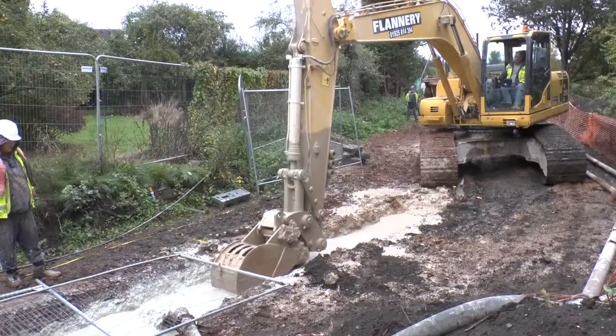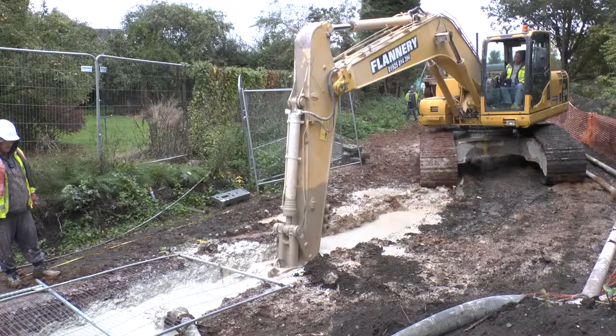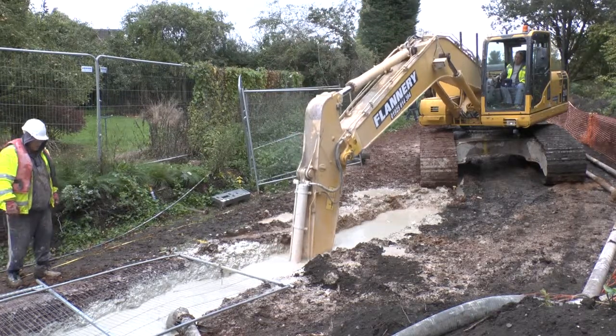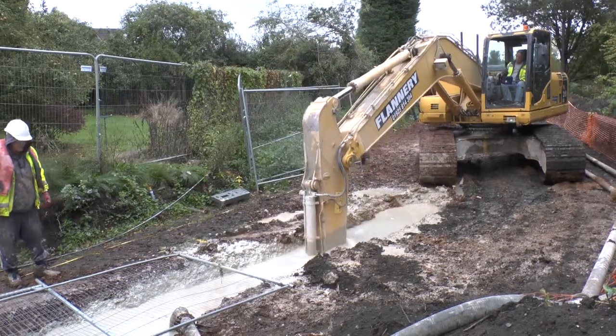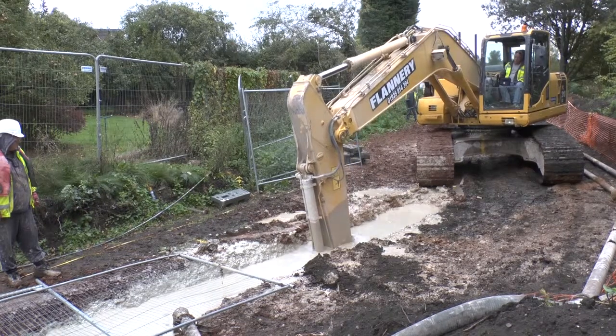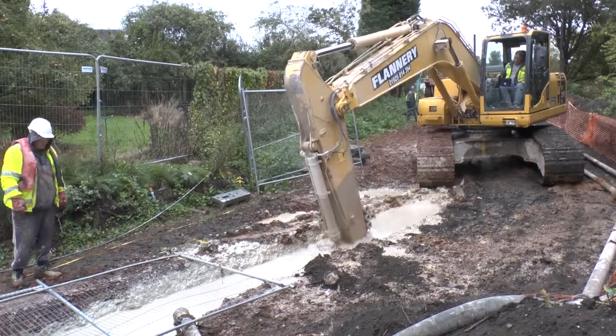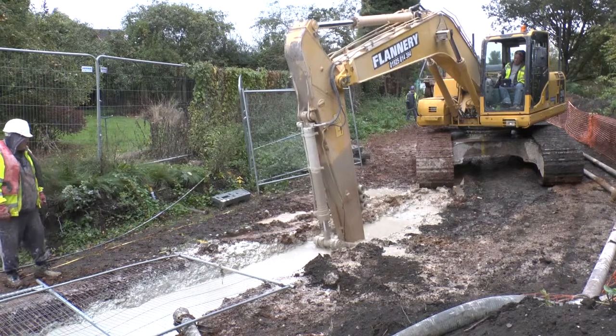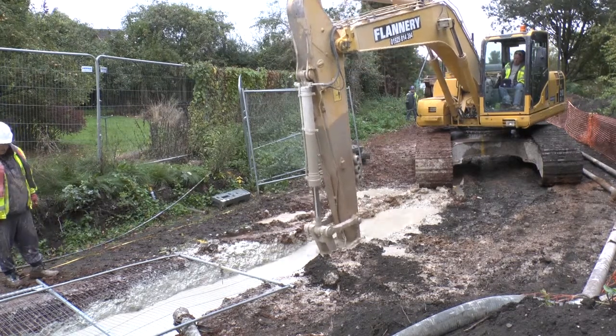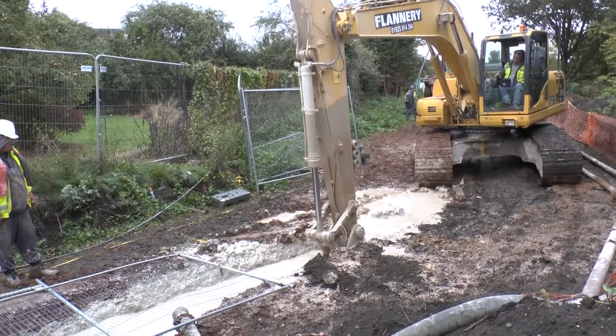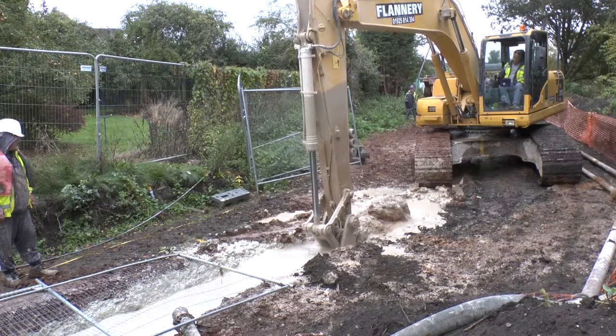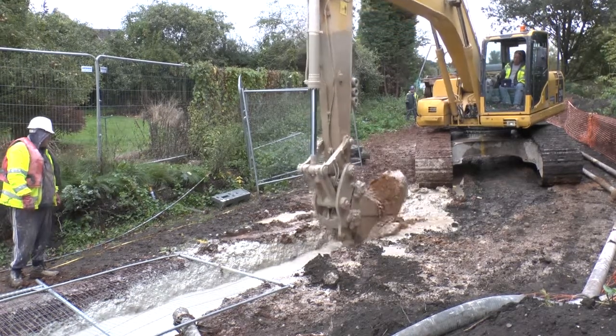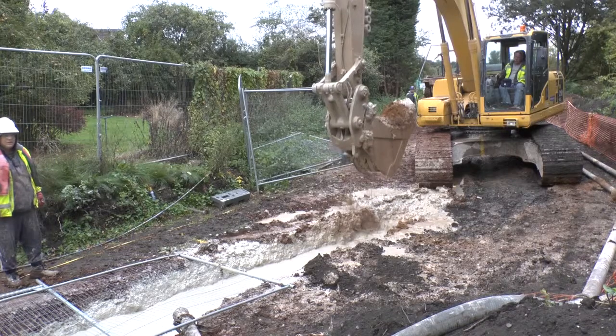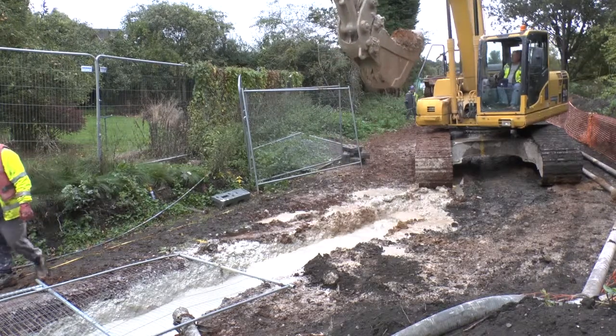To form the trench we simultaneously excavate the trench with a 360-degree excavator. In this particular case it's about a 13-ton machine, and while simultaneously excavating we keep the trench topped up with the cementitious slurry. Whilst we're digging the trench itself, as I said, we use a 360 excavator. We're excavating through the slurry itself, so all the arisings are coated with the cementitious slurry.